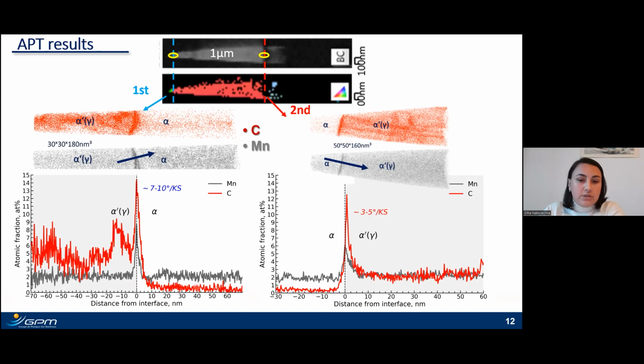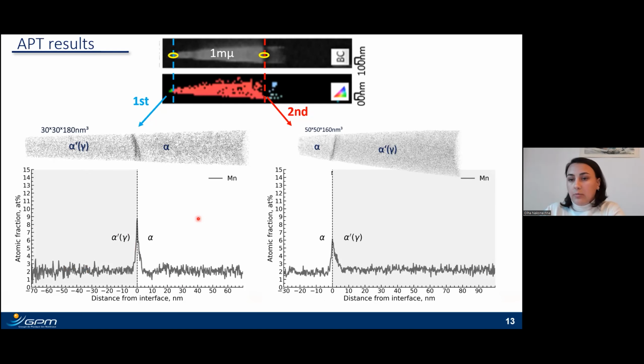It's one of the simplest ways to identify the transformation interface, especially during the first APT acquisition, when we need to stop the run by ourselves. But on the next slide, I will only show you information related to manganese. The first information that can be extracted is the value of the maximum of the manganese peak and the average composition in martensite, austenite, and ferrite.